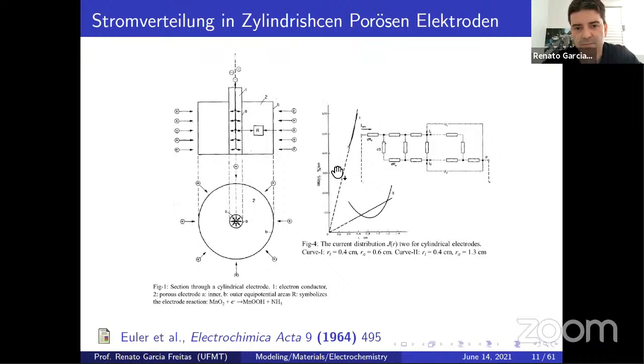So here we have the plot of the total current. It's considered as J, but it can be a charge as well. The total current and here, the radius. So de Levie suggests a model with this transmission line, where the current distribution for two cylindrical pores, the inner radius is 0.4 for both. For curve one and curve two, the inner pore was 0.4 centimeter, like here. And the outer pore is 0.6 centimeter, which is curve one.